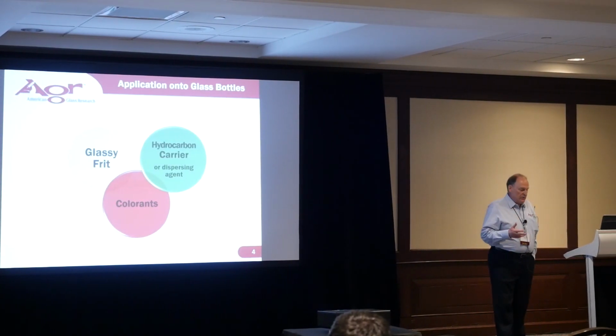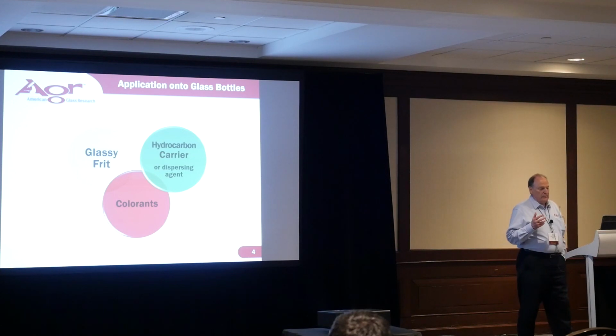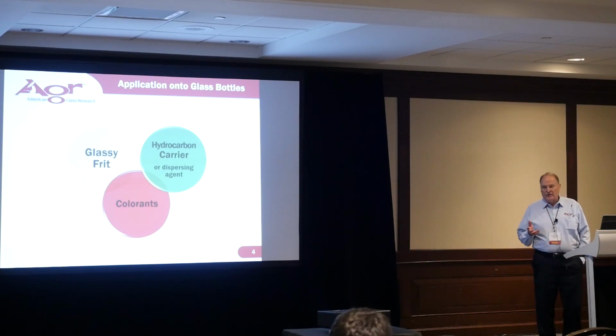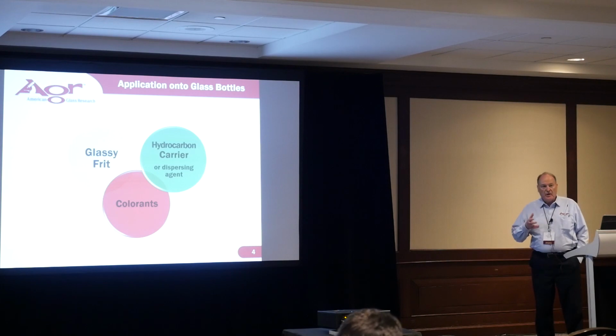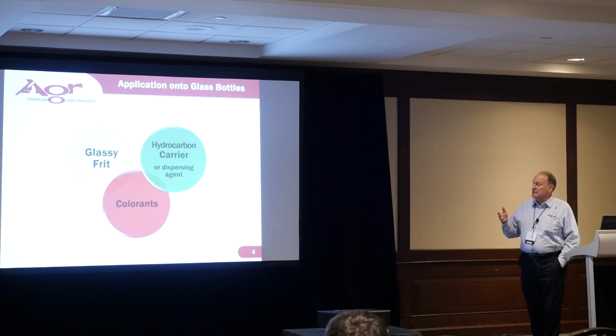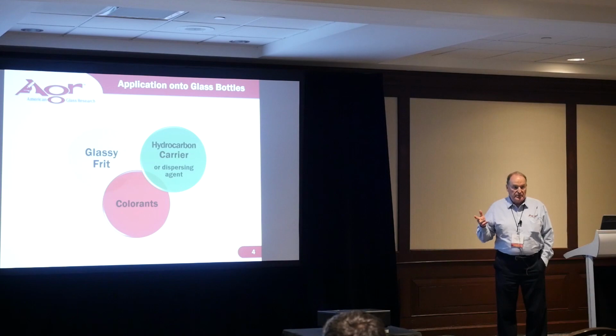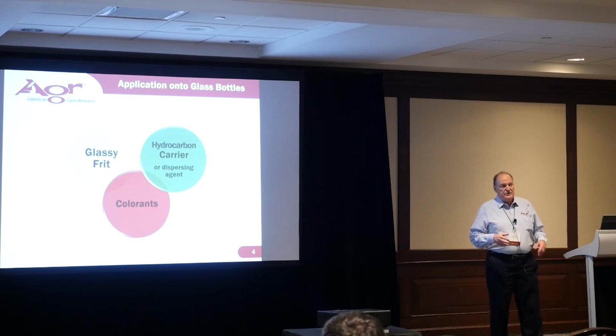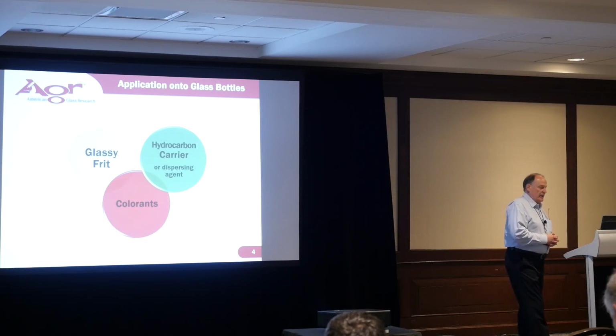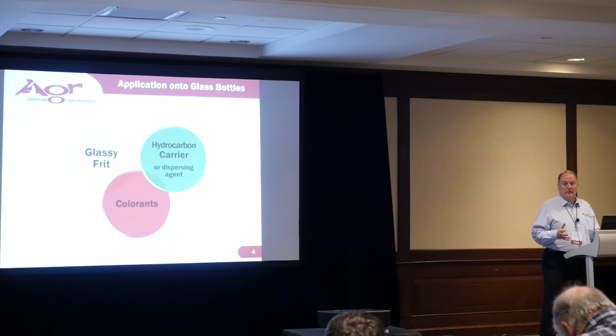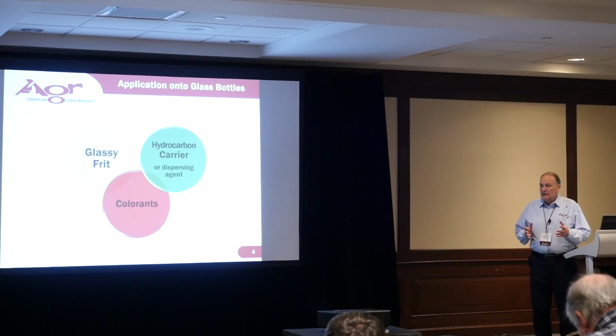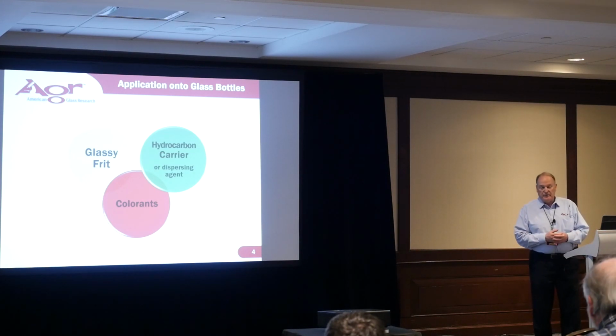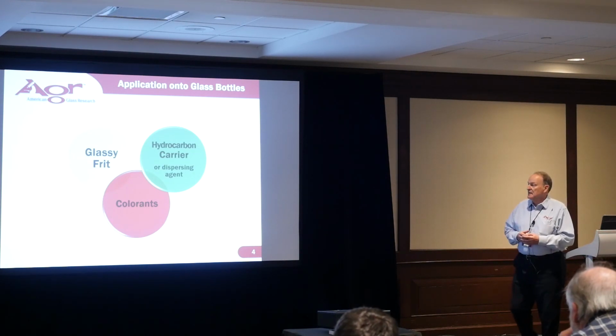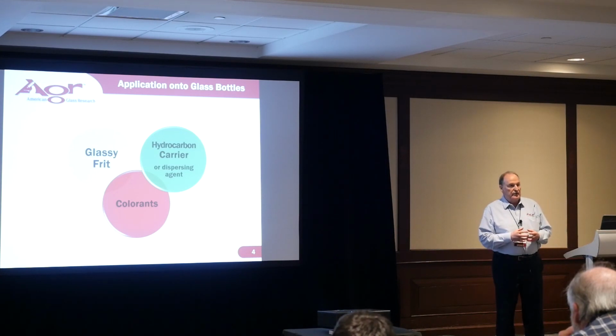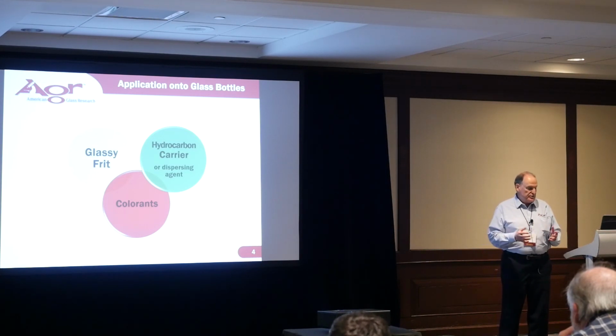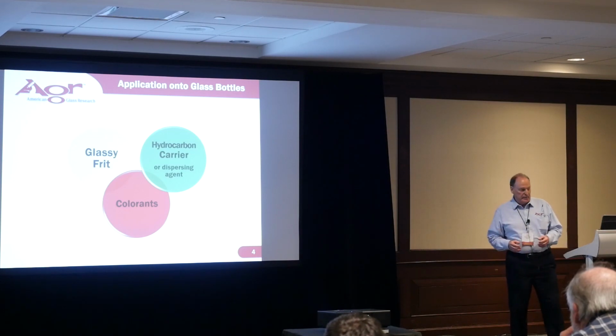Now, in very general terms, when decorations are applied onto glass bottles, the raw materials generally consist of three components. A low melting temperature frit and colorant, which is then dispersed uniformly in some type of hydrocarbon carrier, so that the material, when it's applied to the surface of the room temperature bottle, would be consistent in thickness, and that the frit and the colorant are uniformly distributed to achieve the desired effect of that particular label.